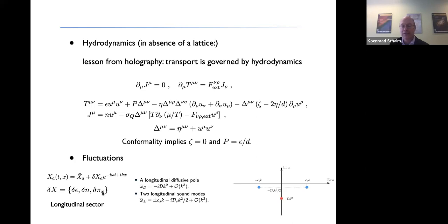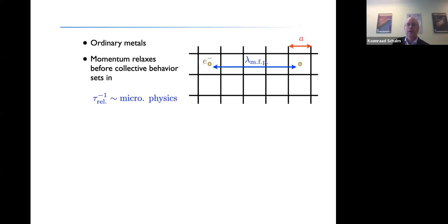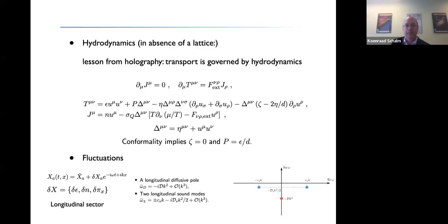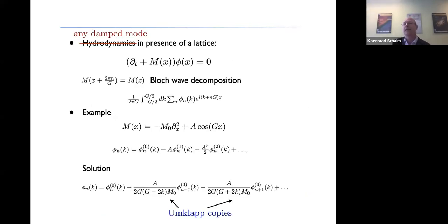And when you do an analysis of this, you find that there are three poles in this system. There's two longitudinal ordinary sound modes that are propagating and are far off. They have a strong real component. And there's one diffusive pole in the system. This is the charge diffusion pole, and that's the one that is ordinarily there. Now, the point is that if I look now in the presence of a lattice, we have to actually redo this